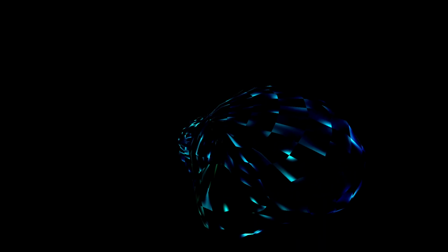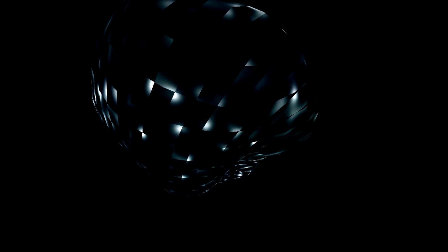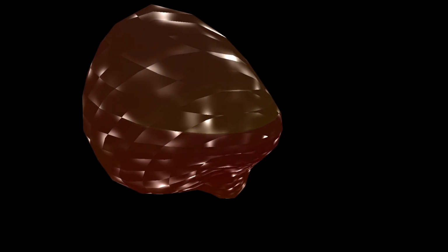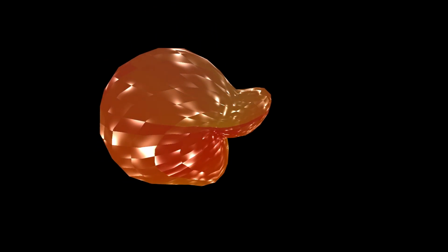A microscopic detective kit. And within PES, a real workhorse technique is X-ray photoelectron spectroscopy, XPS. XPS, okay, uses X-rays. It does. You hit the sample with X-rays, which have enough energy to knock out core-level electrons. Not the outer ones, but the ones closer to the nucleus. Exactly. The tightly bound inner shell electrons. Now, by carefully measuring the kinetic energy of these ejected photoelectrons. Using KE max equals hf minus phi. Yeah, well, rearranged. Precisely. We know the X-ray energy, hf. We measure the kinetic energy, KE, so we can calculate the energy the electron had when it was bound, its